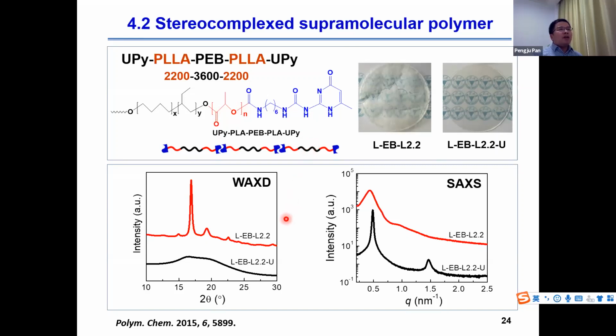The triblock copolymer without a UPy group can crystallize. This crystallization retards the macrophase separation of the triblock polymer. However, for the triblock polymer containing the UPy hydrogen bonding unit, the UPy group destroys the crystallization of PLA and PDLA chains due to the strong confinement effect of the UPy group. The supramolecular polymer forms a layer structure through the macrophase separation.